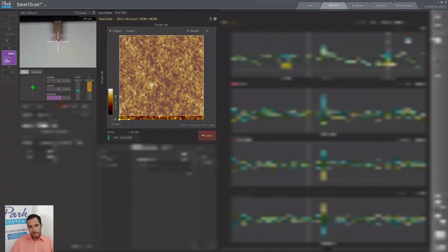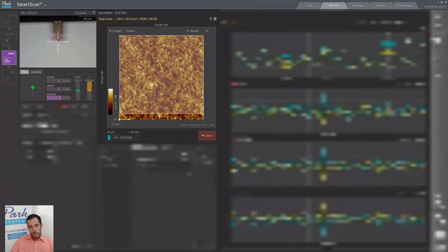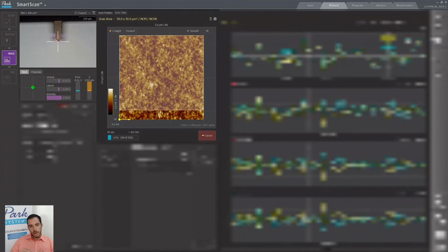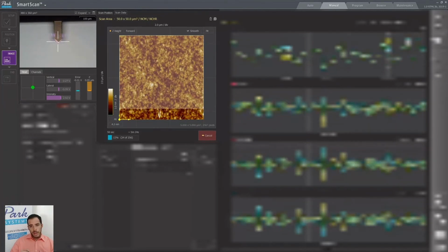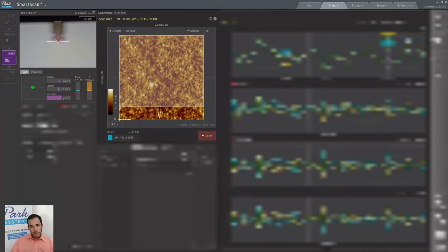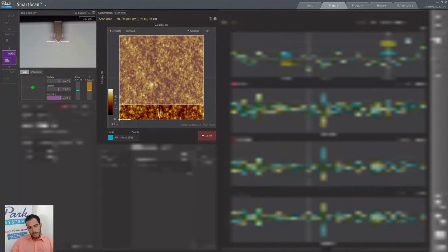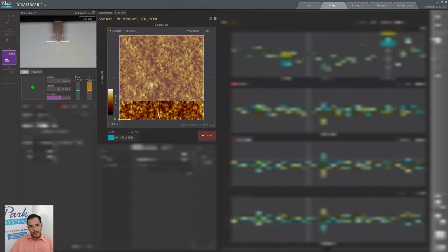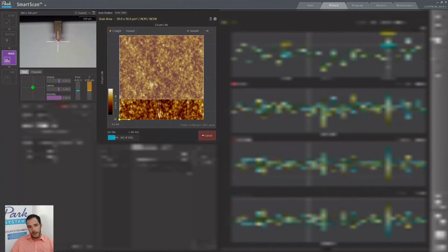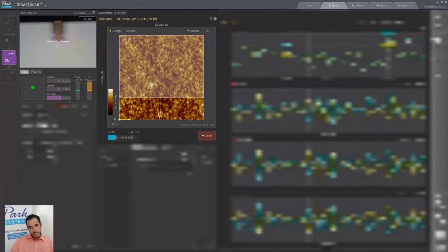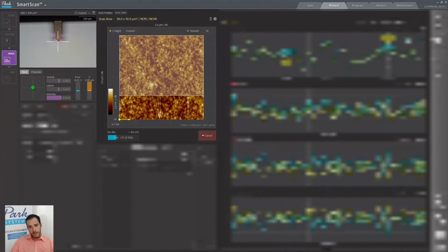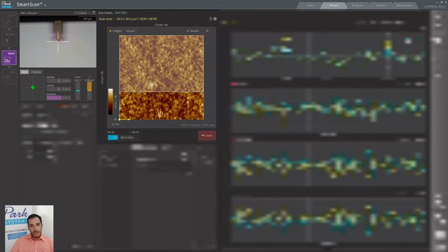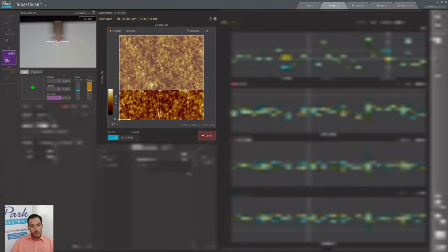our fine grooves. As we remember, the lower row was three lines, the middle one were squares, and the upper one were circles. Right now we can start seeing the lines. We can see that from left to right, the left one is a little bit more blurry. This is because we just applied 100 nanonewtons, and the ones in the center and the right are more clear because we applied a bigger amount of force. Right now we should start seeing the squares.